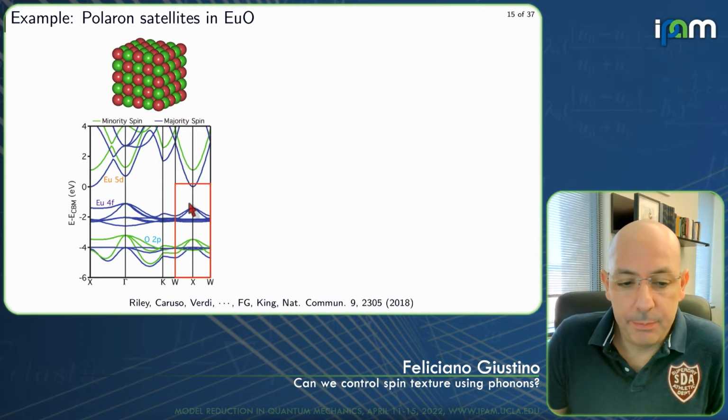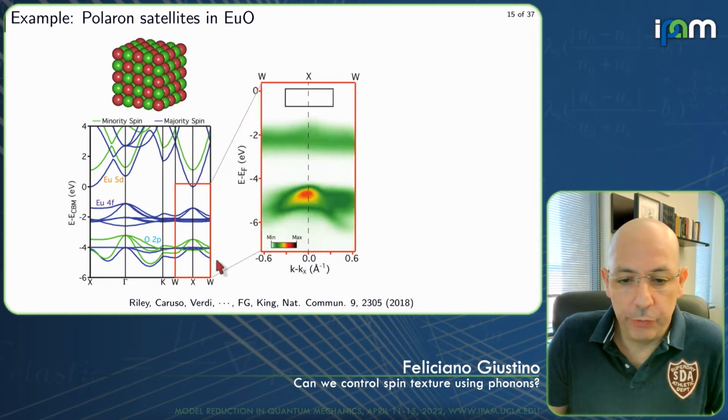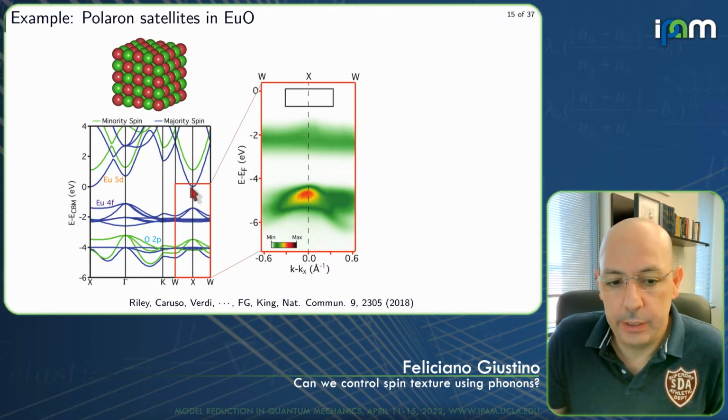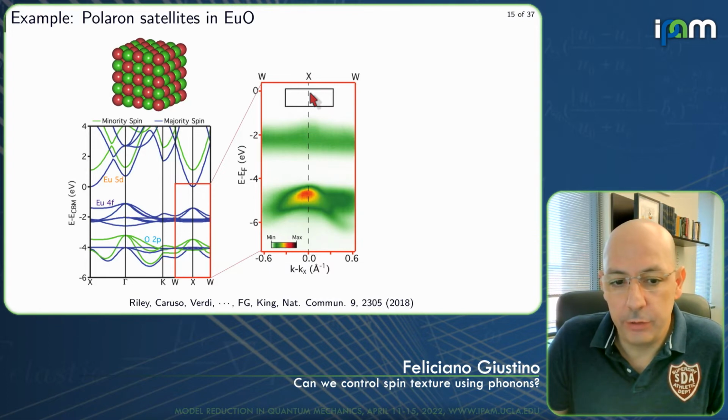Now we can analyze the band structure by using photoelectron spectroscopy. Our collaborator King did measurements on this. What you find from photoelectron spectroscopy is that this band here is essentially the one that you see here. Then the top of the valence band here, you can see it here. In the system, they also introduced electrons in the conduction band bottom here, but you don't see anything. This is simply because the density of electrons in the conduction band is so much smaller than in the valence band that you cannot see any peak.